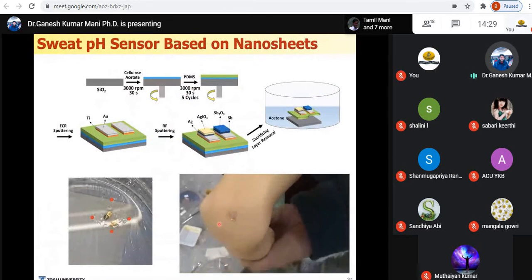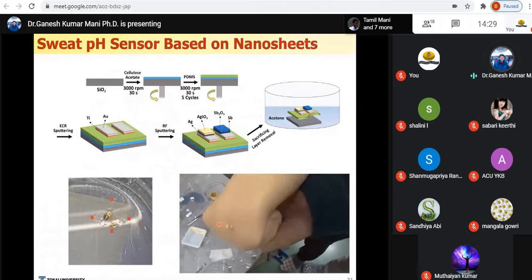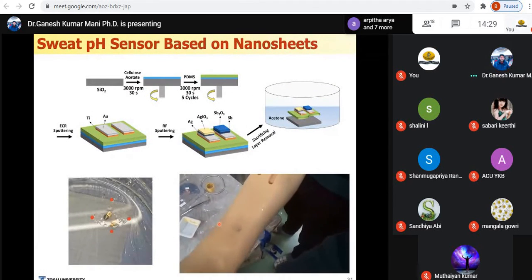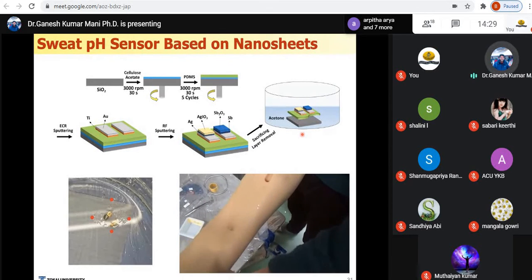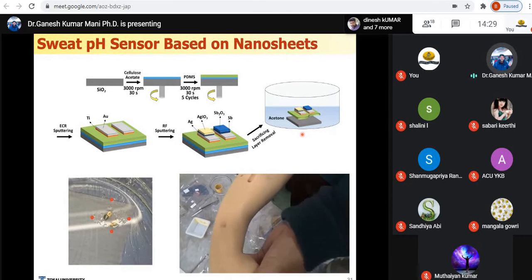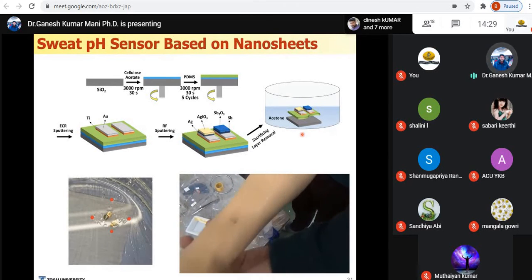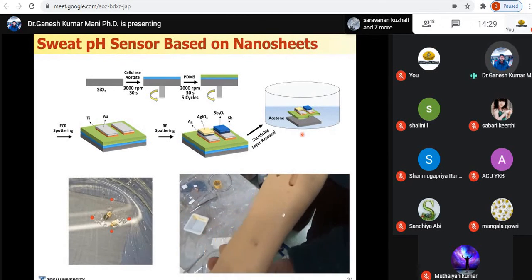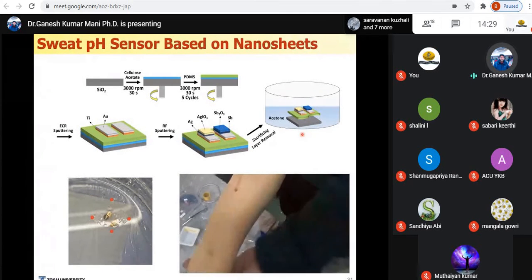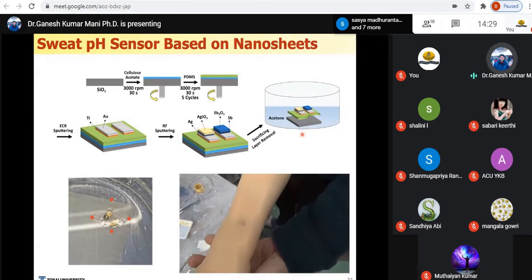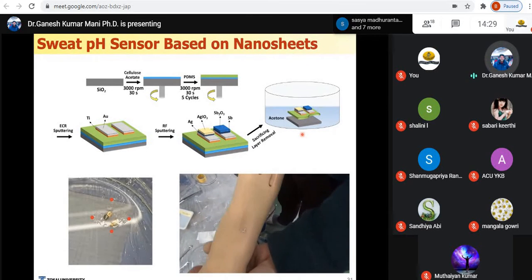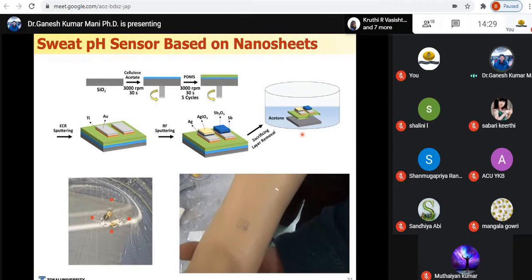This is the production method. We use the sacrificing layer method. Initially we take silicon oxide and deposit cellulose acetate as a sacrificing layer, and then PDMS as a substrate. Finally, after depositing the electrodes, the reference electrode is Ag2O3, which is our own lab-developed material, and Sb2O3 is the working electrode. After depositing, we can dissolve the sacrificing layer to make the nanosheet freestanding, and then you can transfer it onto your skin. When you connect it with the electric components, it can measure your pH.